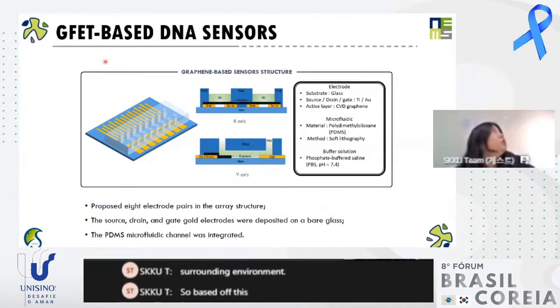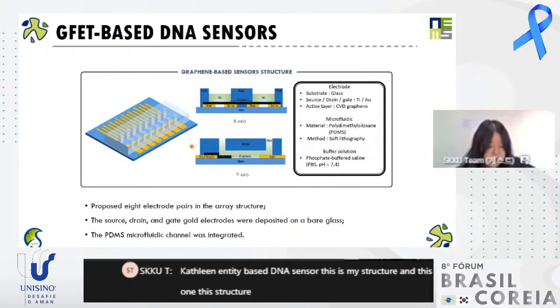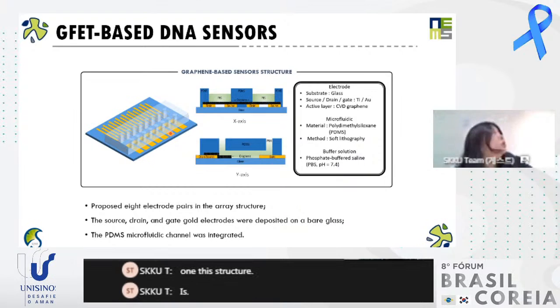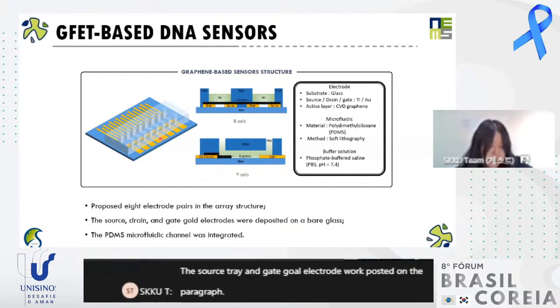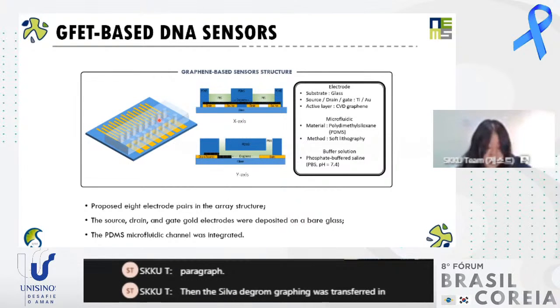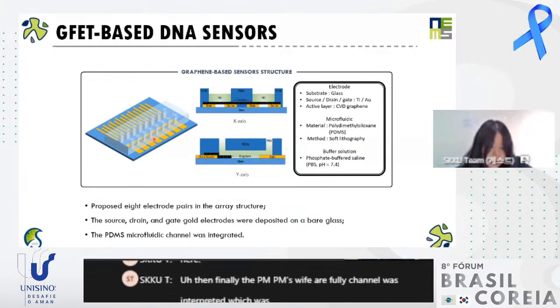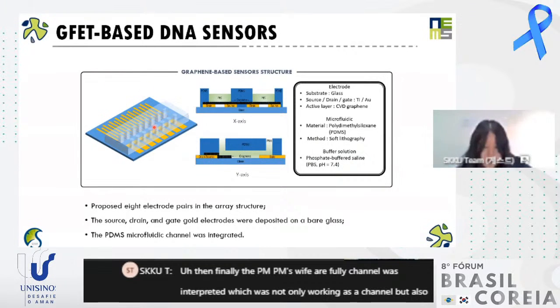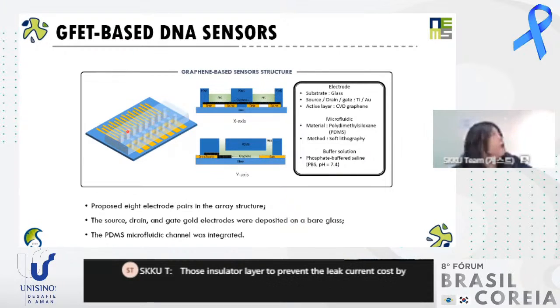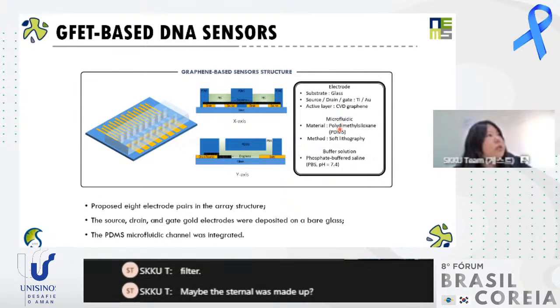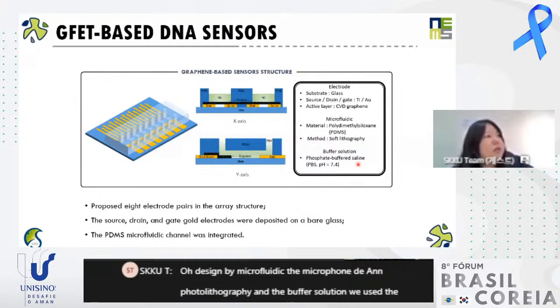Based on this graphene FET-based DNA sensor, this is my structure. The source, drain, and gate gold electrodes were deposited on the bare glass. Then the CVD-grown graphene was transferred here. Then finally, the PDMS microfluidic channel was integrated, which was not only working as a channel, but also as an insulator layer to prevent the leak current caused by stored electrolyte. The PDMS channel was designed by microfluidics and photolithography, and for the buffer solution we use PBS solution.